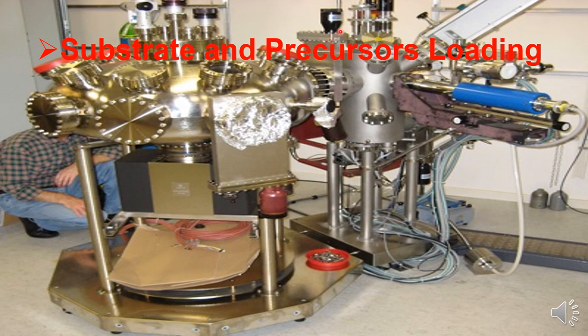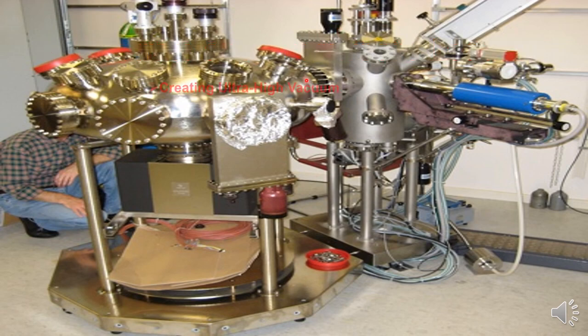After loading the precursor and substrate inside the molecular beam epitaxy chamber, the reaction chamber is highly evacuated. Dear student, please note that the high vacuum used in molecular beam epitaxy is somewhere around 10 raised to power minus 8 to 10 raised to power minus 10 torr. This pressure is very low, so it is quite difficult to attain such an ultra high vacuum.